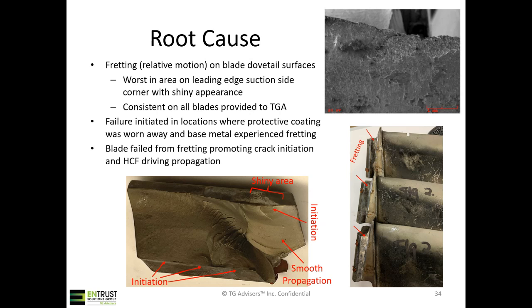But when you have something such as that significantly off schedule stator vane, that's going to greatly increase the vibration these blades see, and that can lead to that coating actually being worn away and then the base metal being exposed. And once that starts fretting, then your material properties are significantly reduced, and that's when you can get crack initiation and ultimately failure. So overall, it was determined that the blade failed from fretting, promoting crack initiation, and then high cycle fatigue driving propagation.